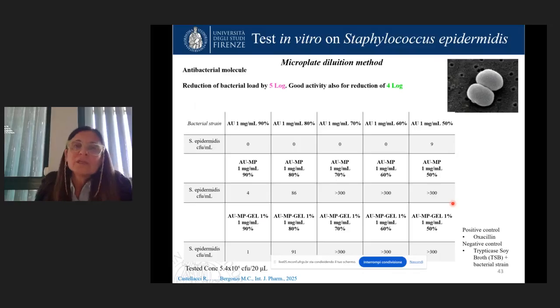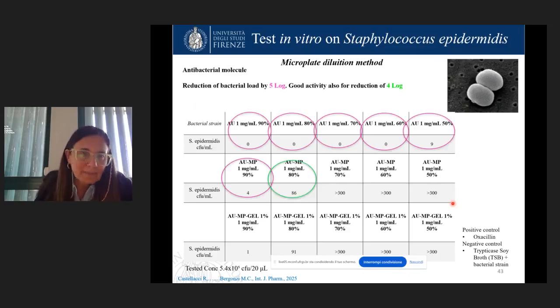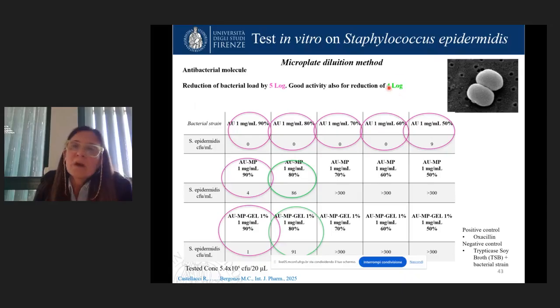We tested the micelles loaded with usnic acid, but also the gel that contains micelles with usnic acid, in vitro for the activity on Staphylococcus epidermidis. And the results showed that both micelles and gel maintain the antimicrobial, antibacterial activity of usnic acid. We consider for activity a reduction of viability of about 5 logarithm, a reduction of bacteria cells of 4 logarithm. In this case, we observed that both polymeric micelles and also usnic acid in the topical formulation have the same antibacterial activity as usnic acid alone.